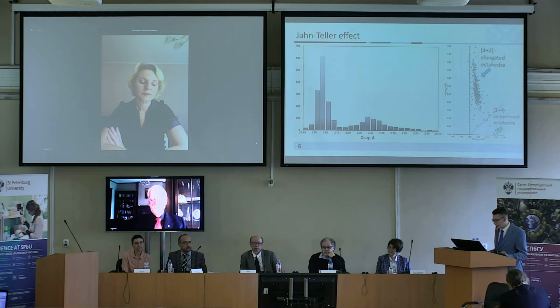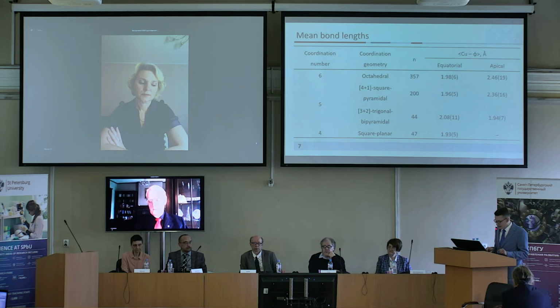Such a distribution of bond lengths in octahedrons limits the entry of copper atoms into solid solutions, and therefore leads to the formation of new mineral species, which explains the anomalous mineralogical distribution. This conclusion is confirmed by the statistical analysis of bond lengths in all most frequent geometries. The results are shown in this slide. This slide shows the values of standard deviations.